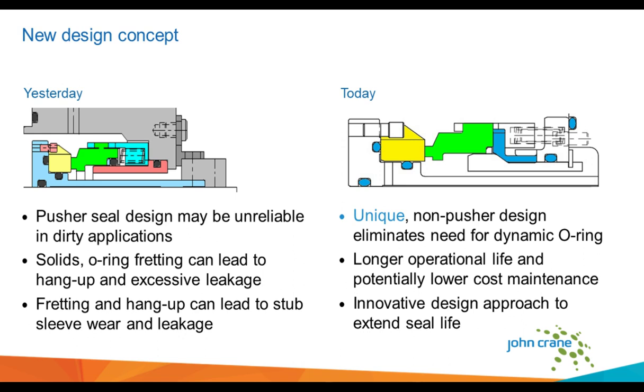It tracks the primary ring, but the drive mechanism stays in place, and there's no interaction between the metal and the elastomer ring. So another cause of failure that we saw was the shuttling. The shuttling led us to the secondary seal problem, the O-ring. The O-rings would start to fret, they would leak, they would hang up, and you would have a seal failure. The faces themselves, the sealing interfaces, were normally in very good condition.